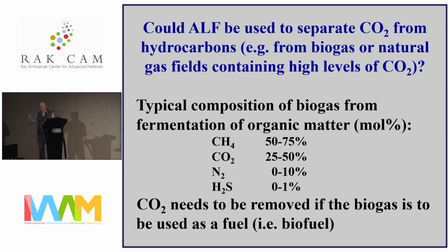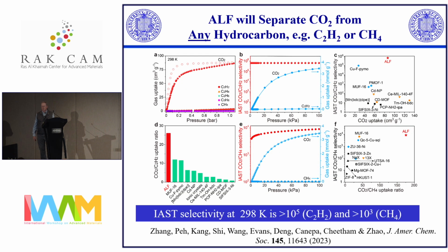Since we know we can separate CO2 from nitrogen, maybe we could separate CO2 from hydrocarbons. And the obvious one to do is separating CO2 from methane, which Mohammed's talked about, because biogas, for example, has a large amount of CO2 in it, depending where and how you make it and so on, but between about 25 and 50%. There are also natural gas wells all over the world that have huge quantities of CO2 in them, again, as high as, say, 30% or so. So we've looked at the question of separating CO2 from hydrocarbons, and there's a lot of data on here.